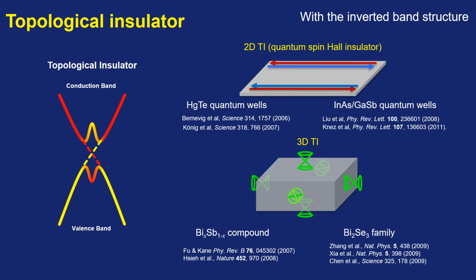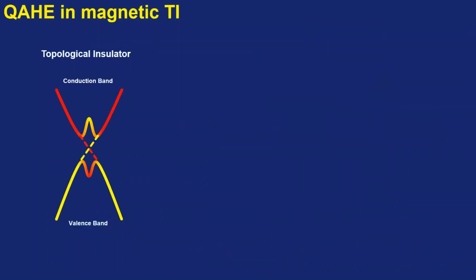My experiment is mainly based on this material, because its band structure is very simple, there is only one Dirac point, and the gap is big, almost 300 meV. Let me show how we can realize the quantum anomalous Hall effect in the topological insulator. This is a topological insulator. This is the Dirac surface state. It is protected by the time reversal symmetry.